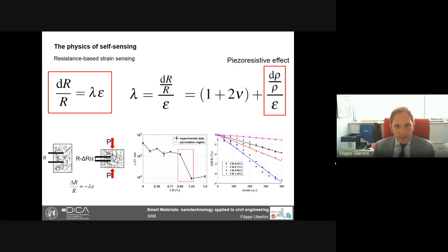Well, the idea in piezoresistive materials, in the smart materials I will show you, is trying to maximize this last term that is associated to what's called the piezoresistive effect, and getting gauge factors that are much bigger than 2 or 2 point something, but can reach values up to hundreds or even thousands. How to do that is to create a conductive network of nano inclusions, nanofibers within the matrix, in such a way that an applied strain produces a change in the interactions between the nanoparticles, which means a change in the overall resistivity of the material.